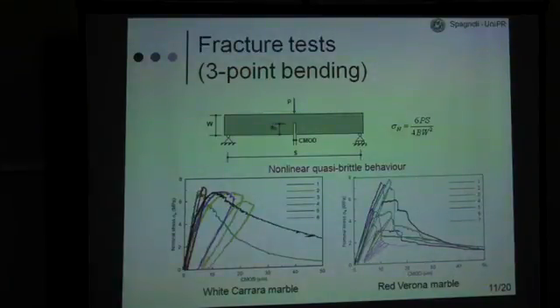What we can see from the very beginning is that there is a non-linear behavior prior to the peak load, identifying clearly this so-called quasi-brittle behavior. So these curves are pretty similar to the curves that you can find for concrete, but as I said at the beginning, there is much less experimental data available in the literature for these natural materials.